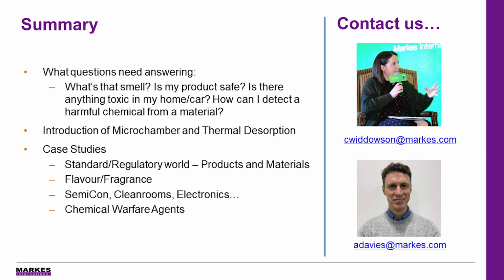Now, what I think might also be the question here is, what about compounds like some semi-volatile or sticky compounds that are renowned for having what we call sink effects, where if you put a material into the Tedlar bag I mentioned, for example, for the semiconductor application, or perhaps the larger chambers, these semi-volatile compounds can emit from the material, but stick within the environment. And that's really where the microchamber is such a unique instrument, because it has such a low surface area. Especially if you raise that sample up with those spacers, then you're minimizing the concern of sink effects.